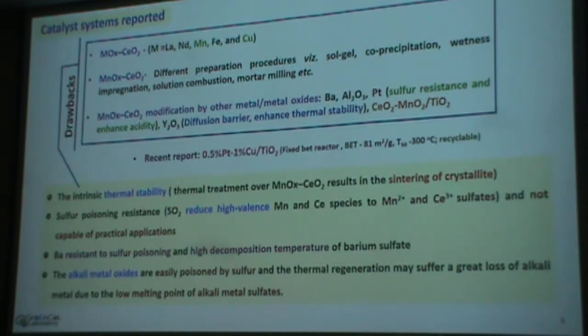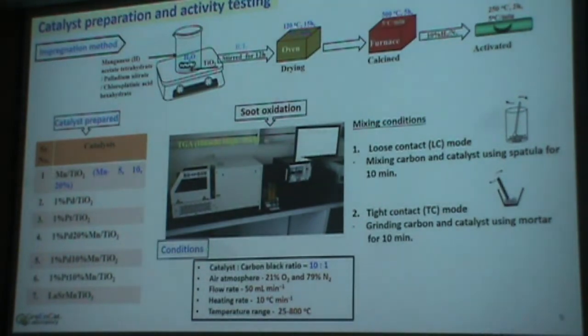So only yttrium oxide is found to be an efficient catalyst system because it acts as a diffusion barrier and enhances thermal stability. Here, I have started with only Mn/TiO2 in order to understand, because TiO2 has high thermal stability and Mn acts as the oxidation catalyst. So I started with a simple catalyst system, the Mn/TiO2 catalyst, and we prepared the catalyst by a simple impregnation method using manganese acetate tetrahydrate as a precursor dissolved in water, dried for 12 hours, calcined, activated and used for the reaction.